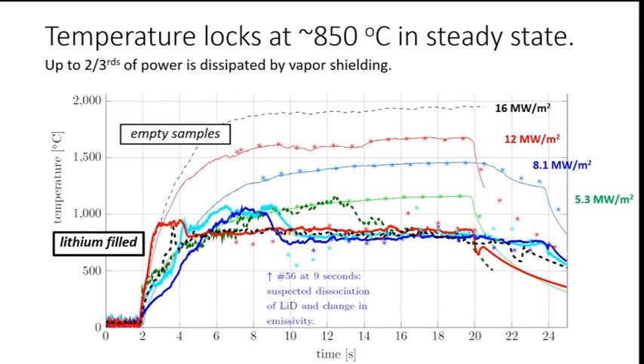So as I explained before, liquid metal evaporates. The liquid metal particles, they heat up, they ionize, they start radiating, they are transported elsewhere. In any case, heat is dissipated and not going to the target anymore. And in fact, we can say from this figure alone that probably up to 2/3 of the power is dissipated by vapor shielding for sure.